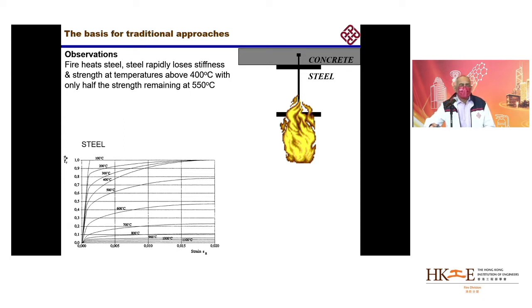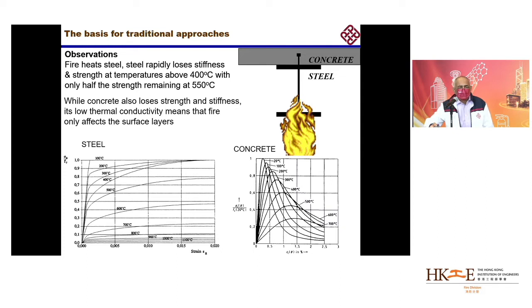And the steel loses stiffness and strength at temperatures above 400 degrees C. The bottom left graph shows you that the strength of steel is about half of the ambient strength when it reaches 550 degrees C. And so that is typically seen as a limit that we must keep.